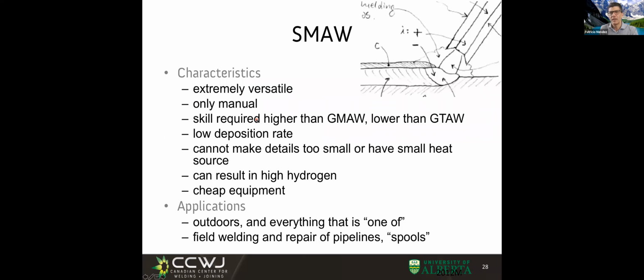The skills are higher than in MIG welding. MIG welding is a more sophisticated machine and thinks for you in many things, but the skill required is much lower than TIG welding. The deposition rate of stick welding is not very high, and the precision is not very high either. You cannot make very fine details like you would in TIG. So when you see sports cars, race cars, airplanes, those are welded with TIG, but not with stick. Depending on the electrodes you use, you can end up with high hydrogen, and even low hydrogen electrodes still typically have more hydrogen than TIG. The equipment is very cheap, as I mentioned.